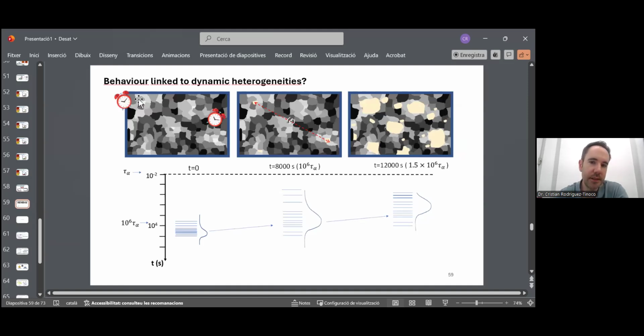So this is kind of a scheme of what I was saying before. Initially we have a distribution of relaxation times, this is the glass, all of them being very large because we have a very stable glass. But each of these regions evolves when we do an annealing at a different pace. Some regions are faster than the others, and these faster regions become liquid sooner. And two regions that become liquid at the same time are separated by a distance, which is 130 micrometers in the case of the most stable glass, which is this kind of dynamic heterogeneity.